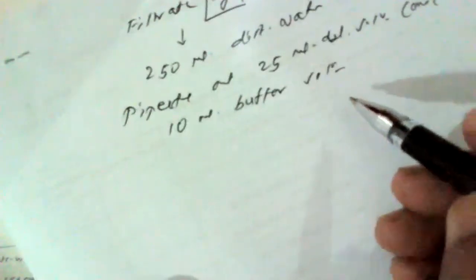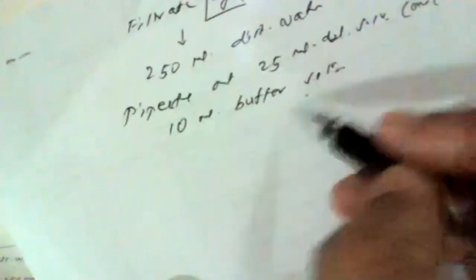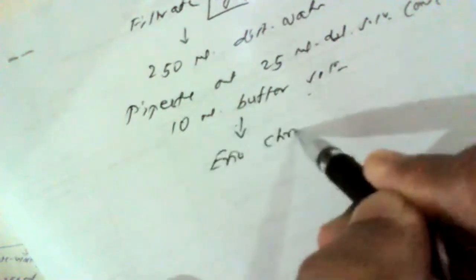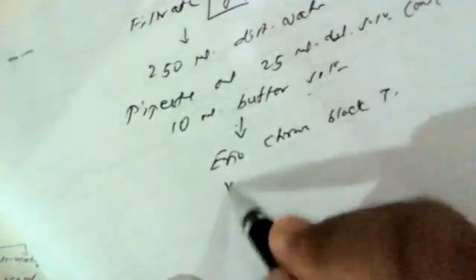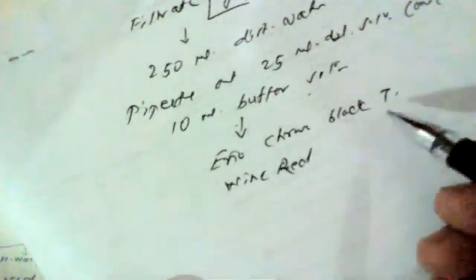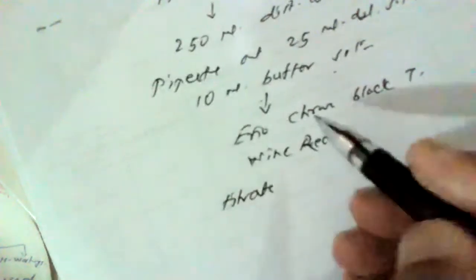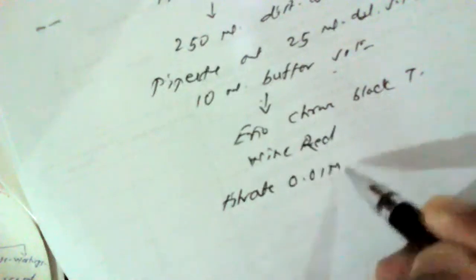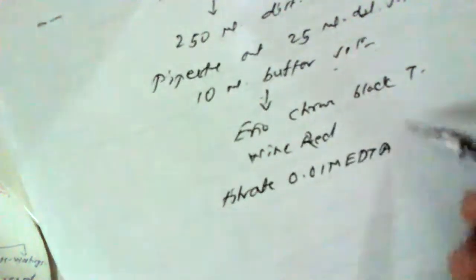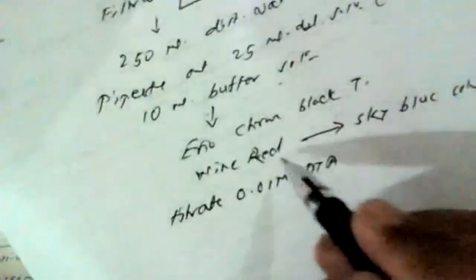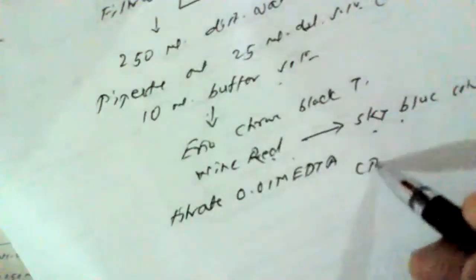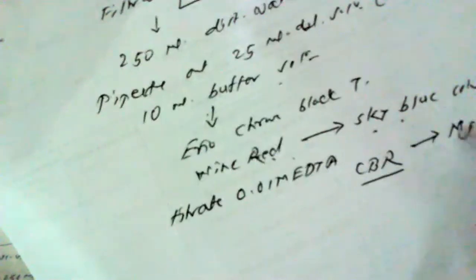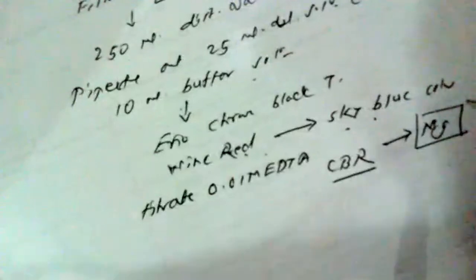To this solution, 10 ml of ammoniacal buffer solution is to be added, which is ammonium chloride and liquor ammonia solution, known as a buffer solution having pH 10. After adding buffer solution, we have to add Eriochrome Black T indicator, which initially turns the color of the solution to wine red. We have to titrate the solution using 0.01 molar ethylenediaminetetraacetic acid solution, that is EDTA solution, until at the end sky blue color is obtained. So wine red to sky blue is the end point of the titration. By knowing the constant burette reading, we can calculate the quantity of magnesium present in the dolomite ore.